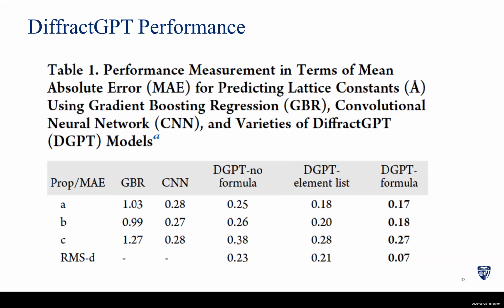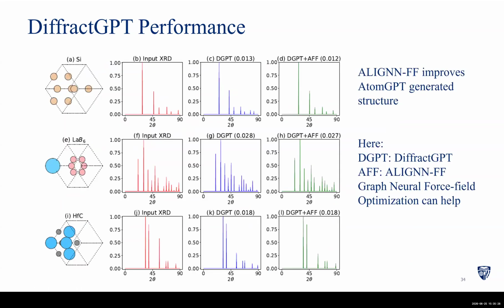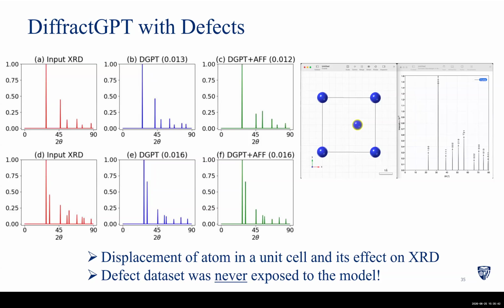Now you can do text-to-text mapping, and it can generalize pretty well, which we are showing here with DiffractGPT against gradient boosting regression, which can, of course, predict only the lattice parameter, not the coordinates. But DiffractGPT can predict both lattice parameters and atomic coordinates. We found that having the full chemical formula in the input gives the highest accuracy, or lowest error. And we can further refine with ALIGNN-FF or any other force field model. And we tested it for silicon, LaB6, hafnium carbide experimental data. These are tested experimental data. We also found, very interestingly, that even though the model was trained on perfect data, it can generalize reasonably well for defect data, where we can displace an atom and see how the diffraction pattern changes, which is interesting.